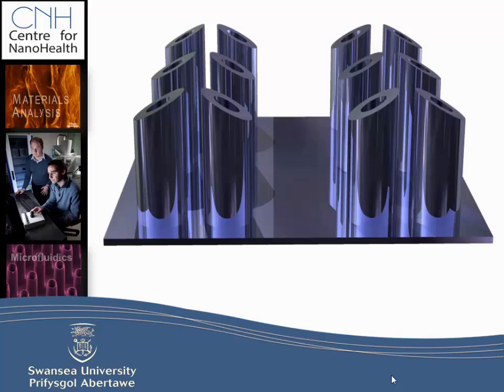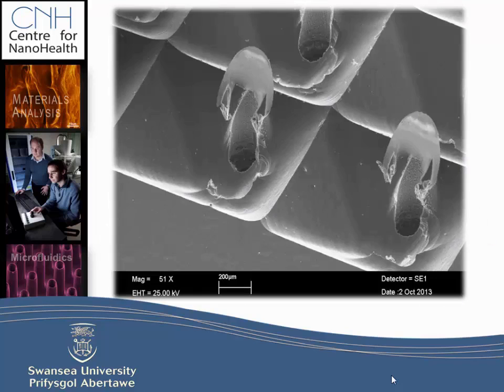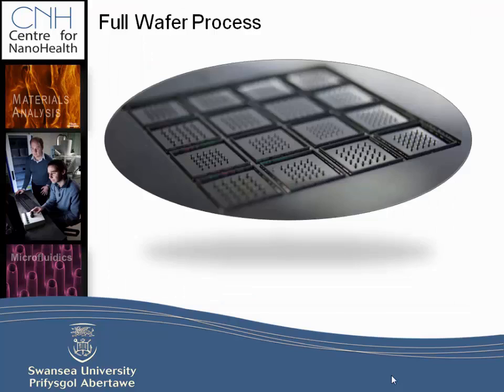This is just an illustration, but our initial results are very good. So we've produced this sharp tip, and this actually penetrates very well into the skin, and you can get it right into the skin. These microneedles are up to 1 millimeter in length, and we think they're around the longest produced that is in the plane of the wafer. So not cutting into the wafer horizontally, but etching the wafer vertically. Okay. So again, full wafer process.